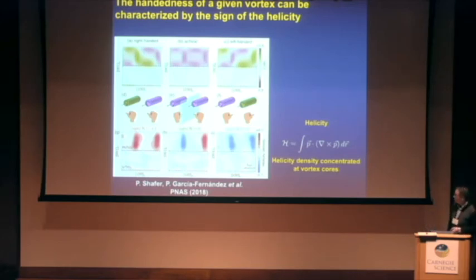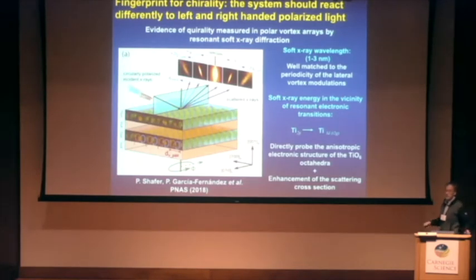So in the last couple of minutes, that's the theoretical predictions. The fingerprint for chirality would be a different reaction of the system under different circularly polarized light, left or right-handed. And this was precisely the experiment that was carried out in the group of Professor Ramesh at the University of Berkeley, where they were using soft X-ray diffraction. Soft X-ray because of three reasons. First, the wavelength of the soft X-ray is well matched with the periodicity of the vortex, anti-vortex, or clockwise, counterclockwise vortices. The energy of the soft X-ray is very well matched with the resonant transition between the titanium 2p and the titanium 3d.